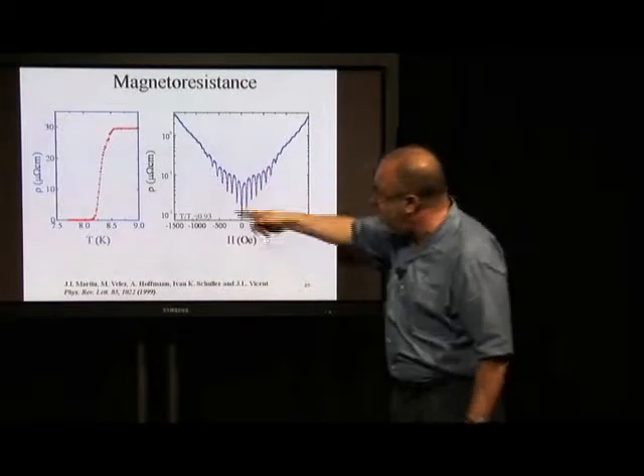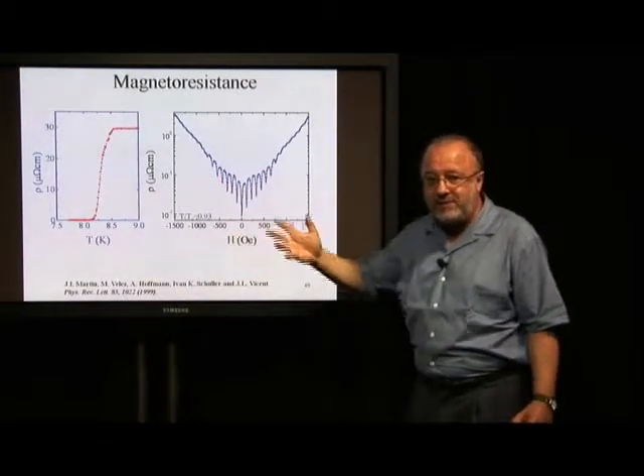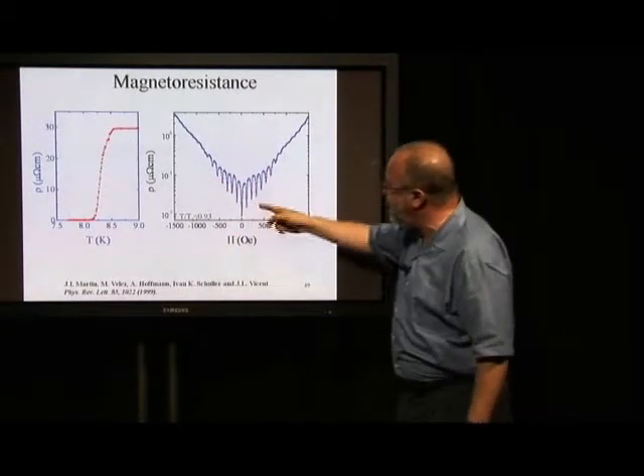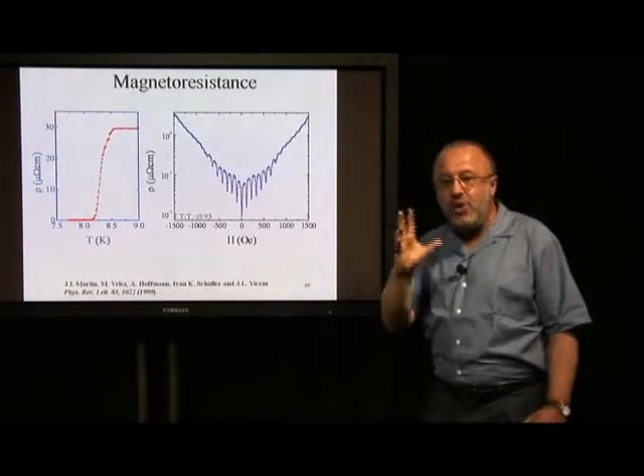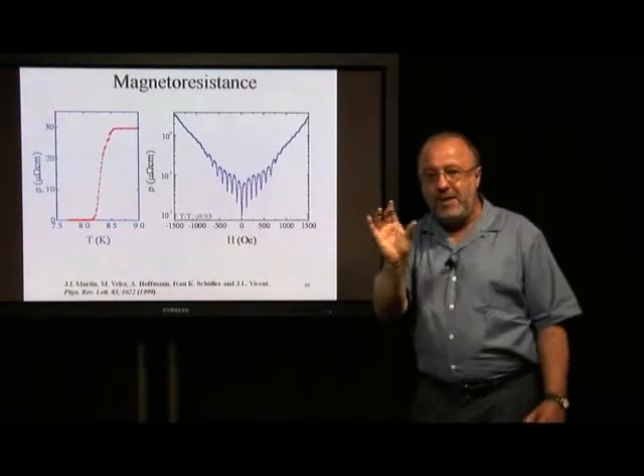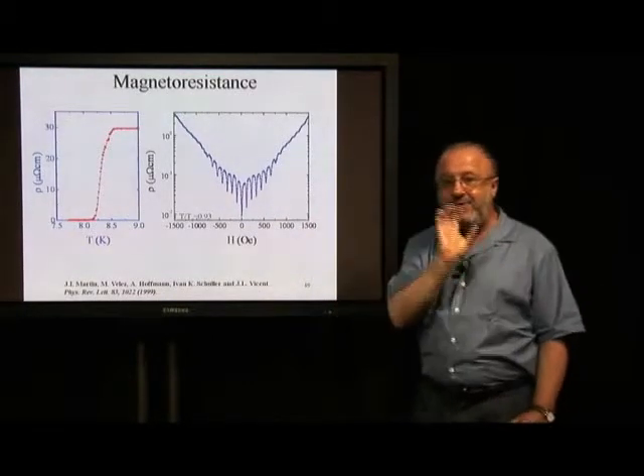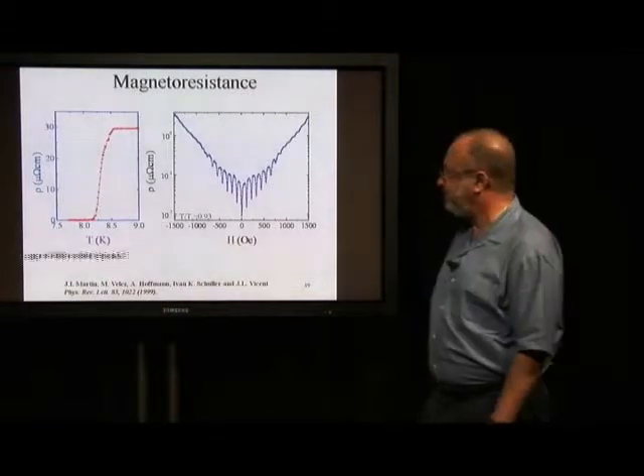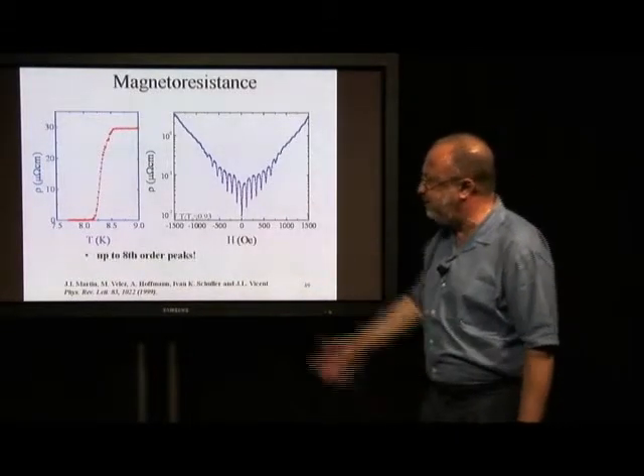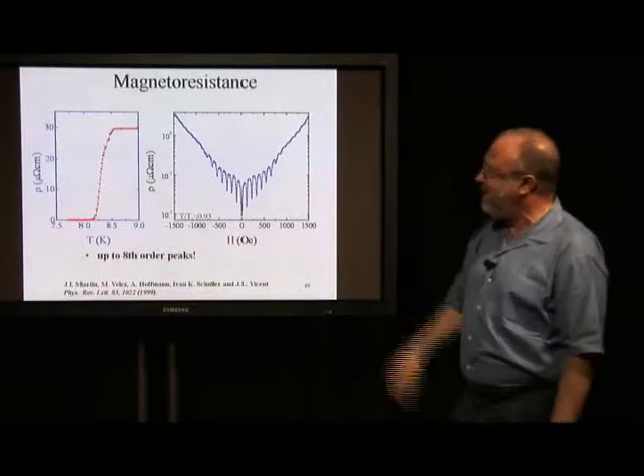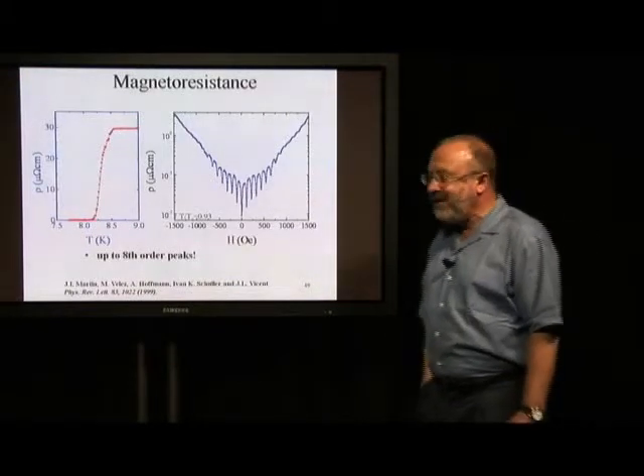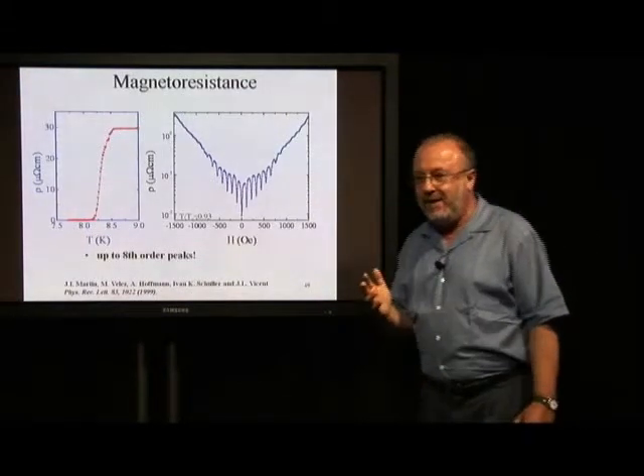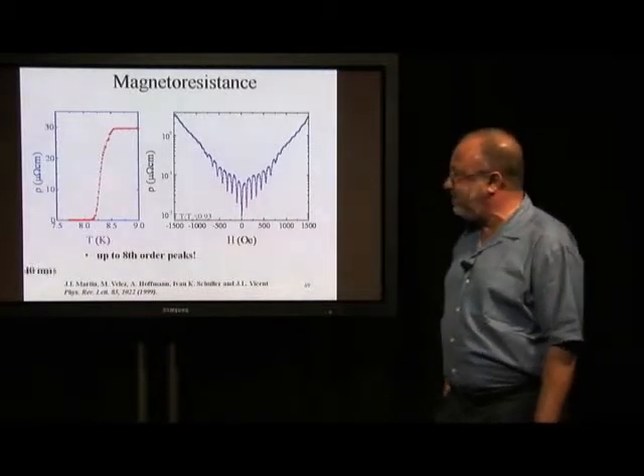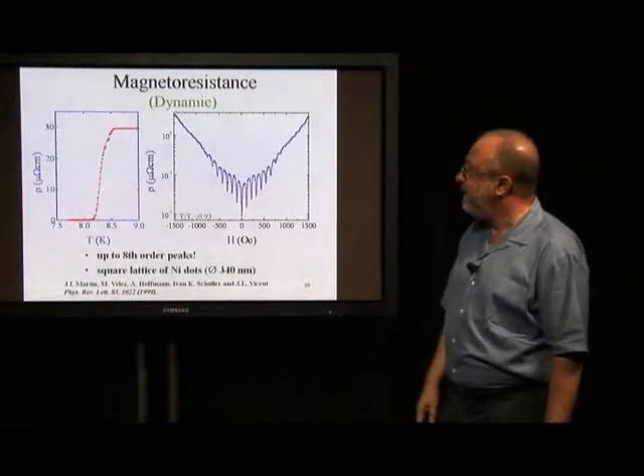And these here are huge kinks, they're huge effects, factors of 10, factors of 100. And these kinks, there's many kinks. The separation of these kinks also has something to do with this matching between the vortex lattice and the artificial array of dots. Well, so for instance, there's up to 8 order peaks. You can tell, again, many of these effects are very interesting, and you don't really have to be extremely knowledgeable in order to realize that something interesting is going on there.